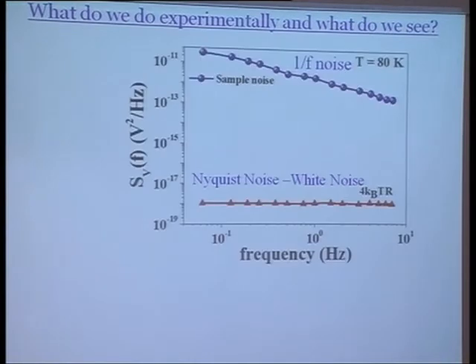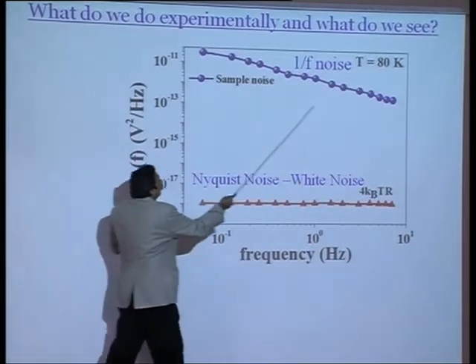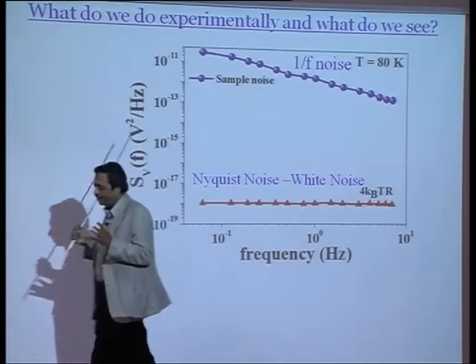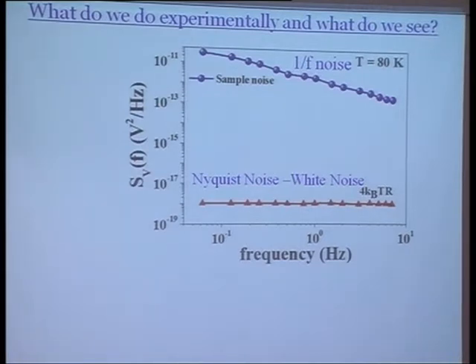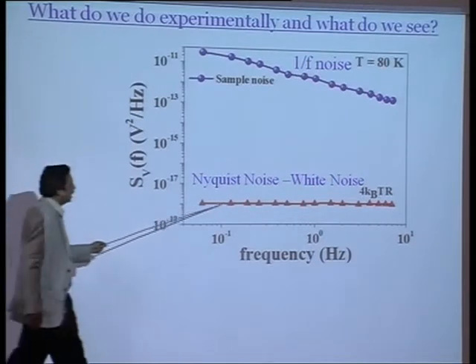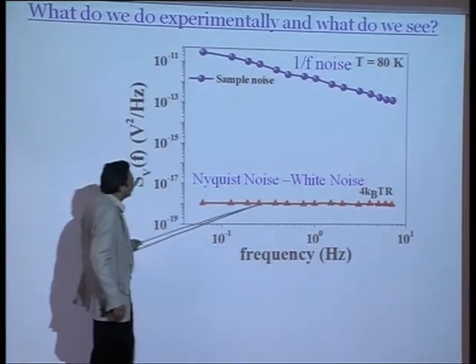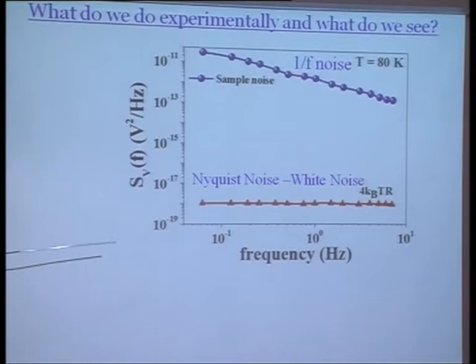It may be. I'm not saying it is not, but it may be. Okay, so that is what we wanted to find out. So experimentally, what do you see? See, this is the 1/f noise part that I talked about before. And this quantity is enormously dependent on the measuring power and has to go as V squared. If the power goes as V squared, you know that you are measuring the proper 1/f noise. And this is why the 4 kBTR is sitting over here. And this is the measured 4 kBTR in the sample that you are talking about.